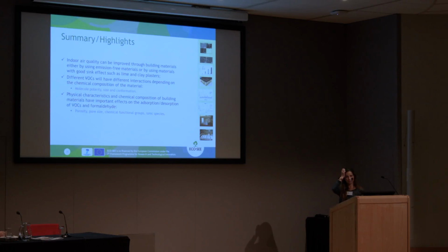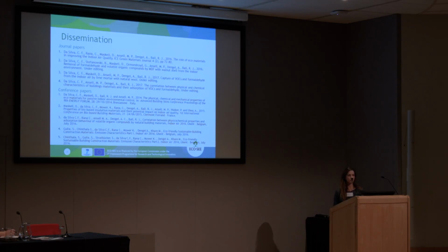So to summarize, can we improve indoor air quality through building materials? Yes, indeed, we can, by choosing emission-free materials as a start, and by using materials with a good sink effect, such as lime mortars and clay plasters. We know that different VOCs will have different interactions depending on the chemical composition of the materials, and the physical characteristics and the chemical composition of building materials have a really important effect on the adsorption and desorption of VOCs and formaldehyde.